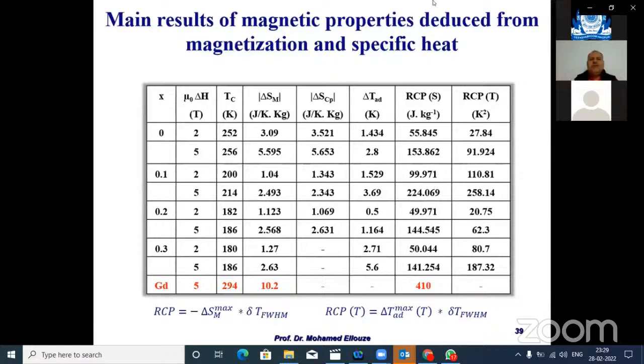Here we have some results about the magnetic properties, from two kinds of results: the variation of magnetic entropy and the variation of adiabatic temperature. We also have the RCP for this kind of sample with different formulas: one using magnetic entropy, and one using adiabatic temperature.